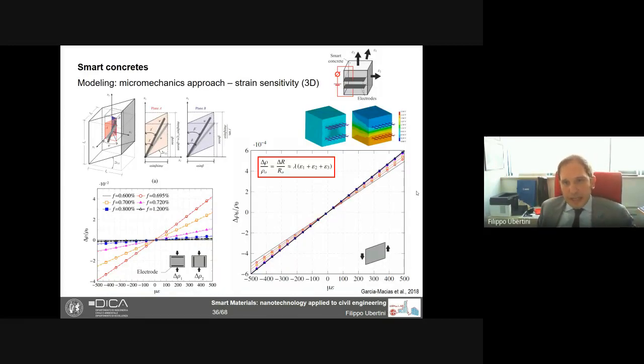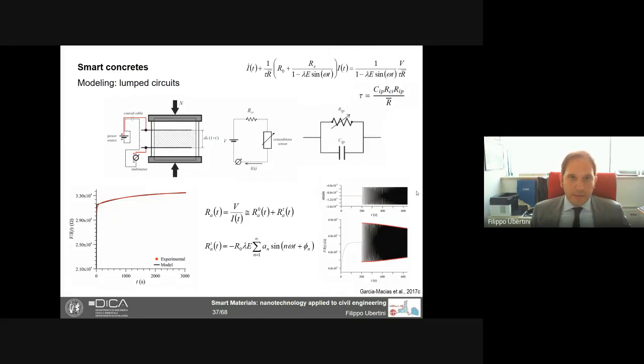This framework was also extended to three-dimensional stresses and strains through a mixed micromechanics analytic approach and a numerical finite element simulation. This was also in a paper with Dr. Garcia Macias as main author in 2018. And what we got from this study was that the shear strain do not really produce big changes in resistivity. Instead, the material is sensitive to the change in volume. So basically, it's sensitive to the linear strains, but regardless of their direction, what we get is actually a sensitivity to volume changes, regardless of how we distribute the electrons.